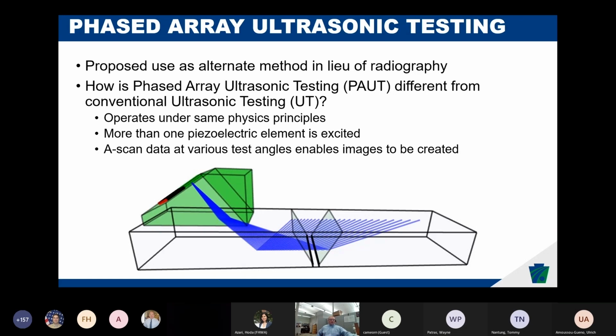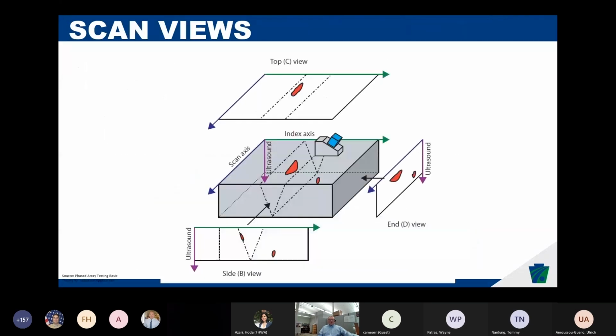What we are changing is the number of piezoelectric elements that we're using and the amount of data that we're collecting. So each individual element is sending out some type of mechanical wave, and we end up collecting A scan data, A scan being your traditional ultrasonic testing output. We end up collecting A scan data at each individual test angle, and what that allows us to do is create 2D images for better interpretation practices, better understanding of what those mechanical waves are interacting with.